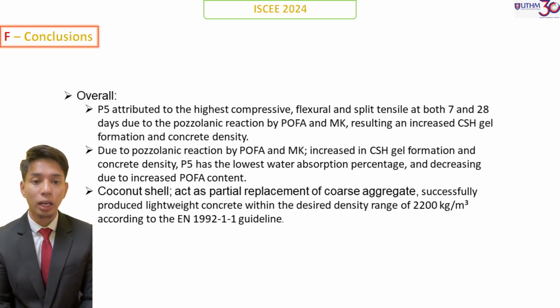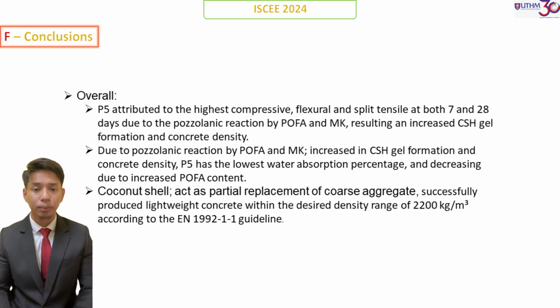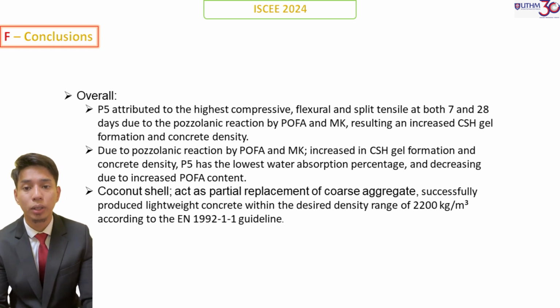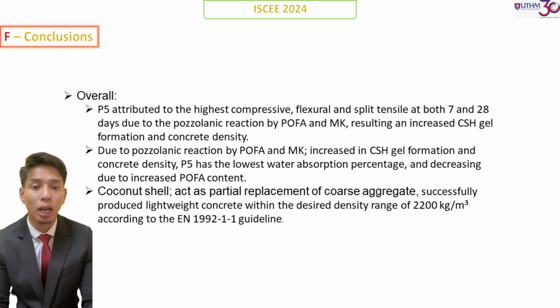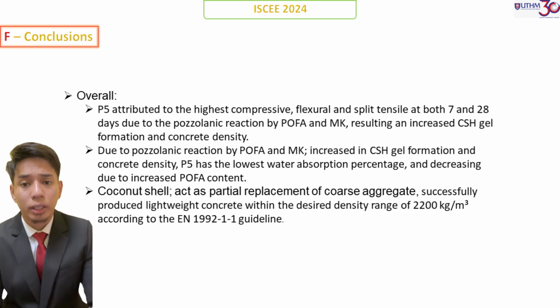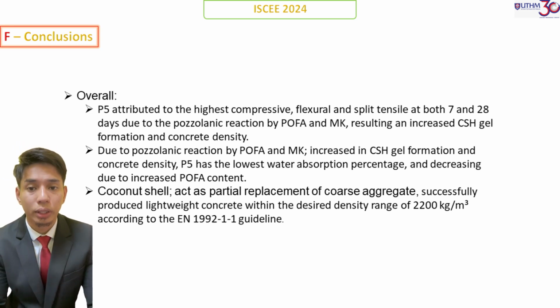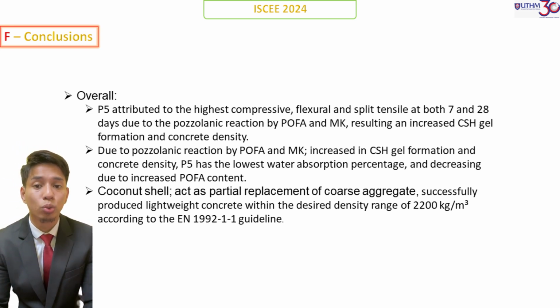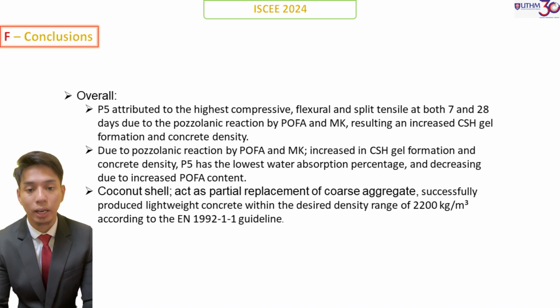The coconut shell, acting as a partial coarse aggregate replacement, successfully produces lightweight concrete within the desired density range of 2,200 kg per meter cube according to the EN guidelines.